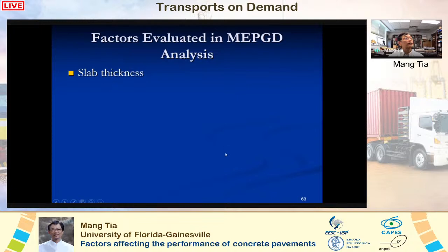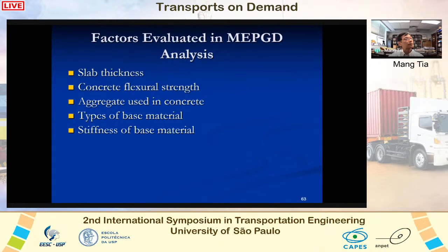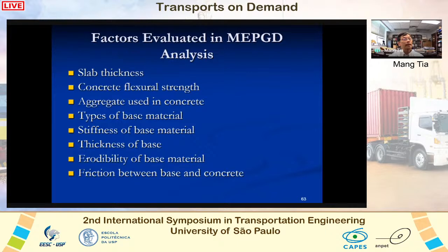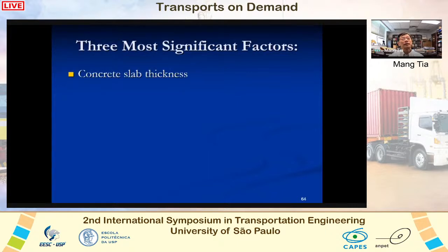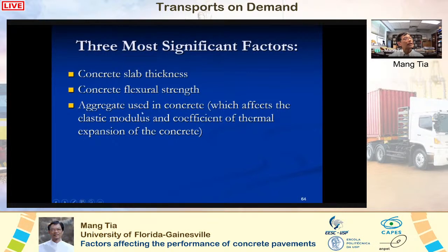The factors evaluated in our analysis include slab thickness, concrete flexural strength, aggregate used in the concrete, types of base material, stiffness of base material, thickness of base, erodibility of base material, and also friction between base and the concrete. And what we found is that out of all these factors, the 3 most significant factors were: 1, the concrete slab thickness, concrete flexural strength, and the aggregate used in the concrete, which affects the elastic modulus and coefficient of thermal expansion of the concrete.